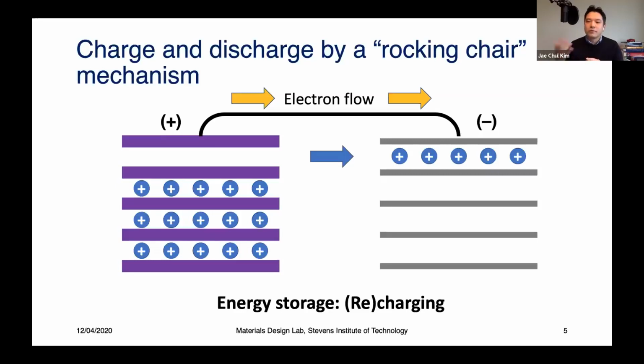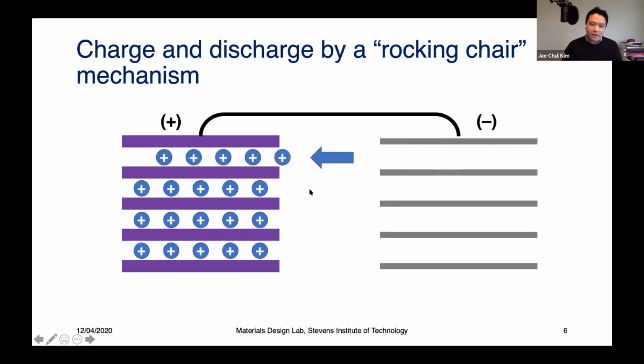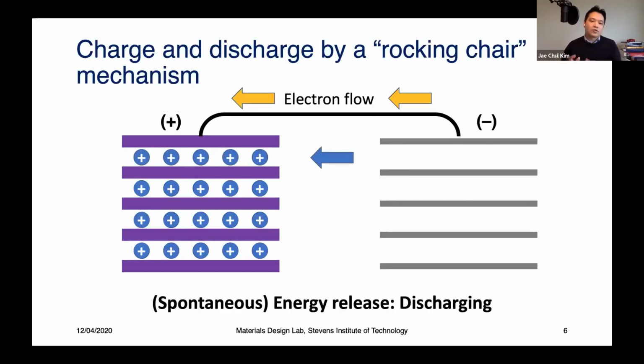sodium leaves the positive electrode material, so it leaves vacancies behind in the material, right? The more sodium you move out of the positive electrode, the more vacancies you are going to generate. So this means that if you charge the material completely, your material now has 100% vacancy with some other constituents. Therefore, your structure tends to destabilize. That's why you don't want to overcharge your material. Okay. And then upon discharge, these ions want to go back to the positive electrode, and this is a spontaneous reaction, and electrons will flow through the outside circuit, performing work, powering your phones and cars, etc.